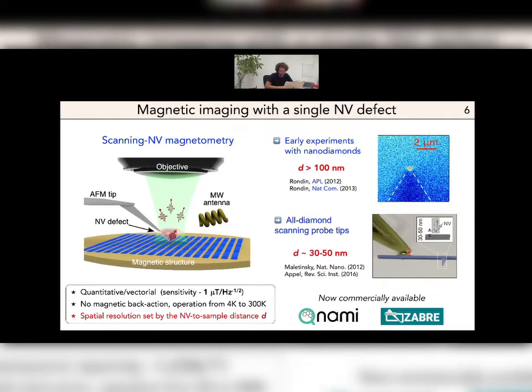The main advantage of this technique is that it's very robust, and you can really go closer to the sample surface, with a probe-to-sample distance in the range of a few tens of nanometers. In all this talk, I will use this kind of all-diamond scanning probe tip.